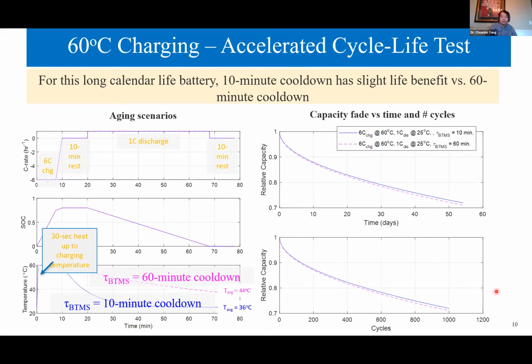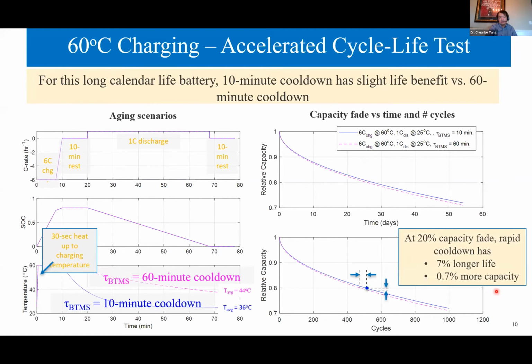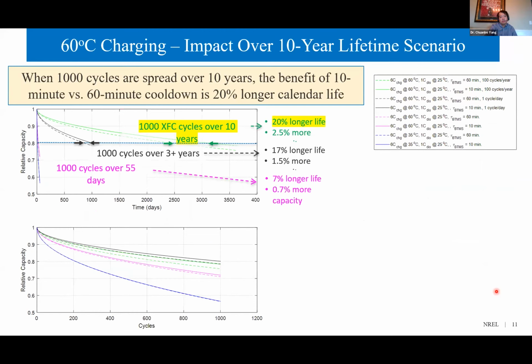For this long calendar life battery during accelerated cycle life testing, a 10 minute cooldown has slight life benefits versus a 60 minute cooldown. At 20% capacity fade, the rapid 10 minute cooldown has 7% longer life. If we consider a real case scenario, for example, 1,000 fast charges occurring over 10 years, 20% longer battery life can be achieved with a rapid 10 minute cooldown.